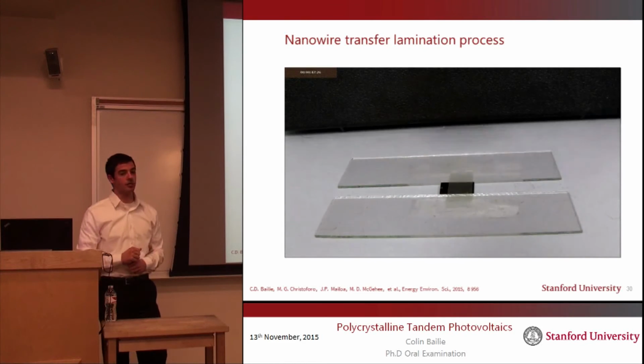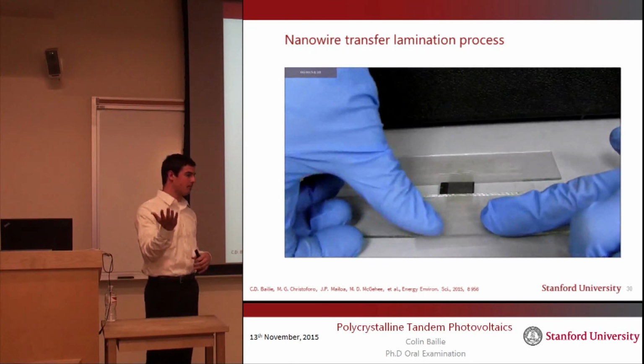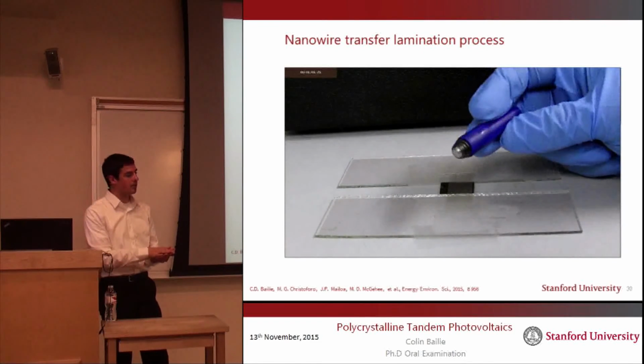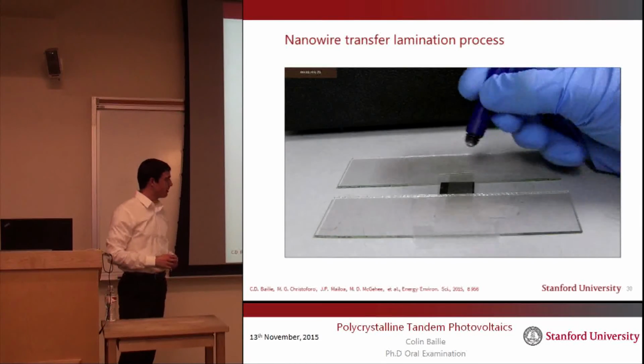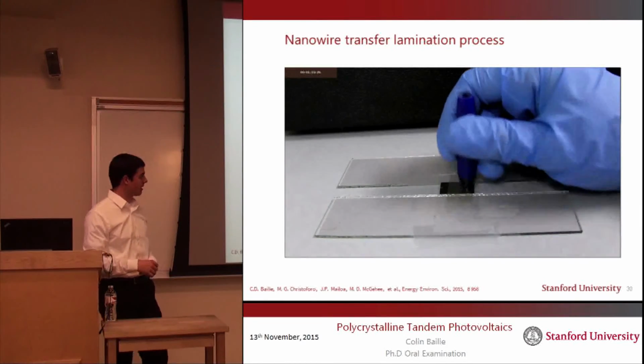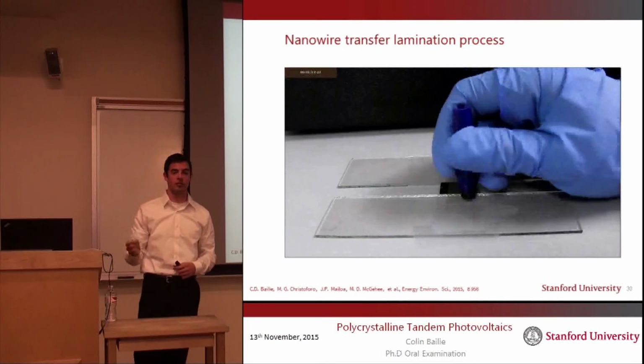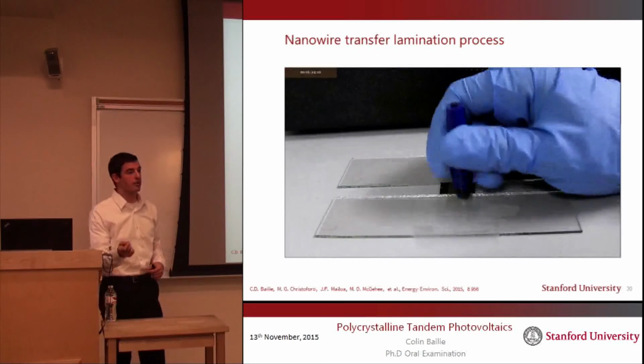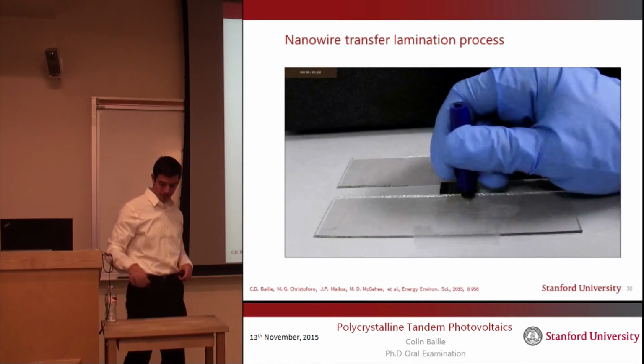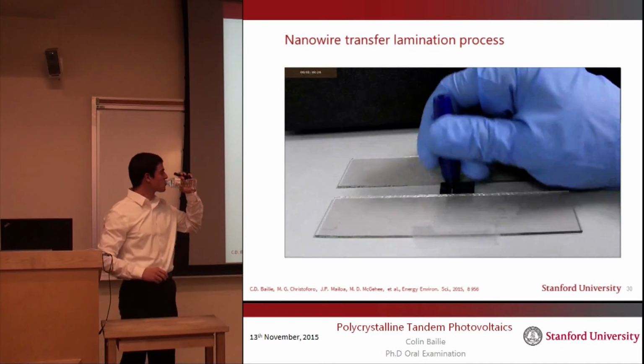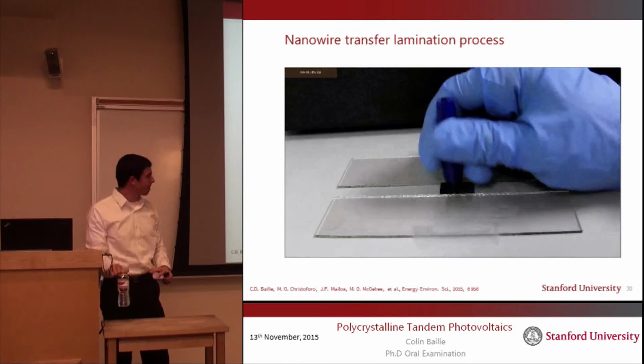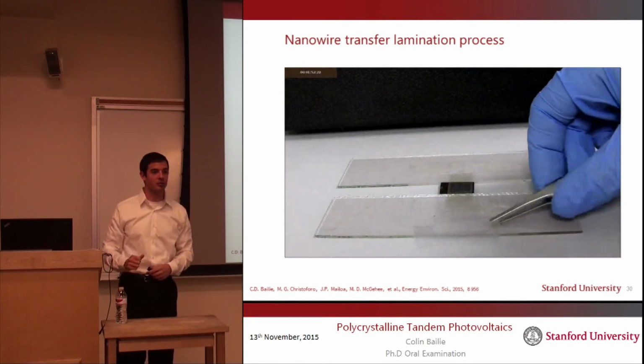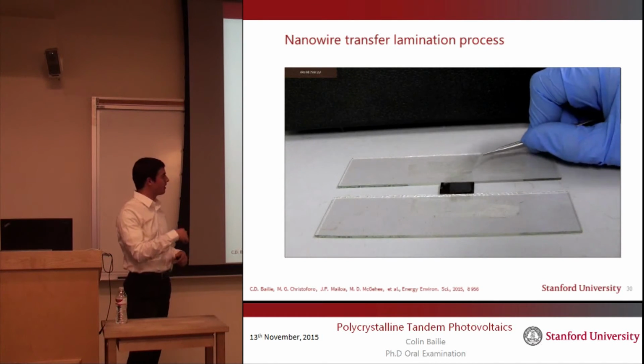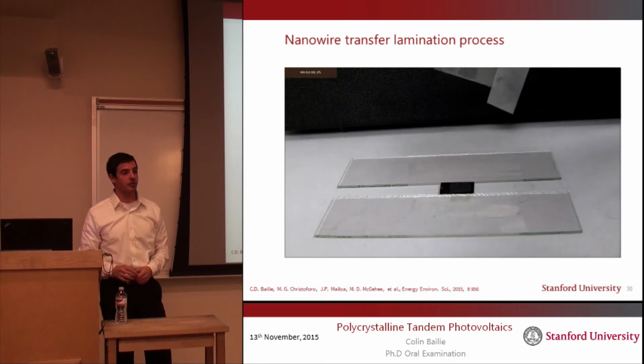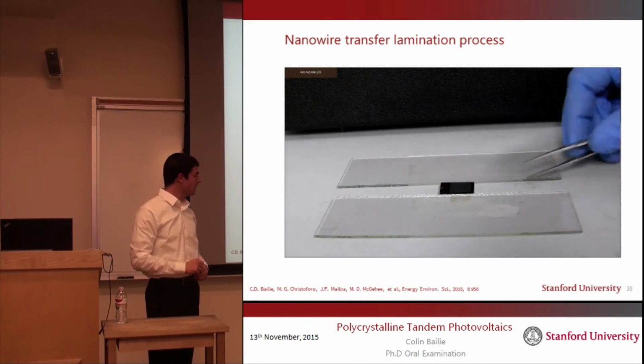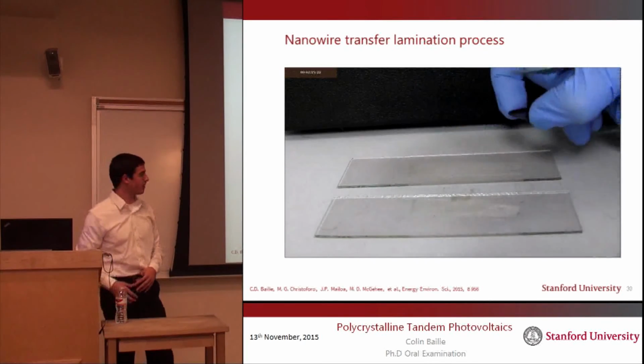And the strategy here now is that we're going to transfer the wires from the sheet of plastic and embed them into the perovskite. And we're going to do that basically by drawing our electrode onto the solar cell. And everywhere underneath this ball bearing where there is sufficient pressure, the nanowires will literally be pressed from the plastic into the solar cell. And so when we're satisfied with how much we've been drawing and we take away our sheet of plastic, we can see that there are no nanowires left on the plastic where we've drawn this electrode, and instead they are on our perovskite solar cell.